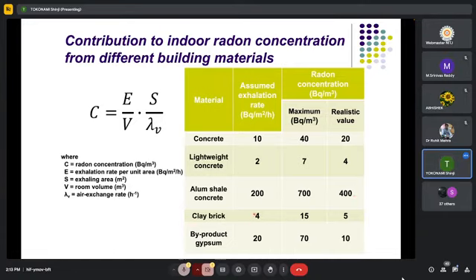Clay brick, when we assume the exhalation rate of 4 becquerel per square meter per hour, the radon concentration will be 15 becquerel per cubic meter as maximum and 5 becquerel per cubic meter as a realistic value. Byproduct gypsum, when we assume the exhalation rate 20 becquerel per square meter per hour, the radon concentration will be 70 as maximum, 10 as realistic value.